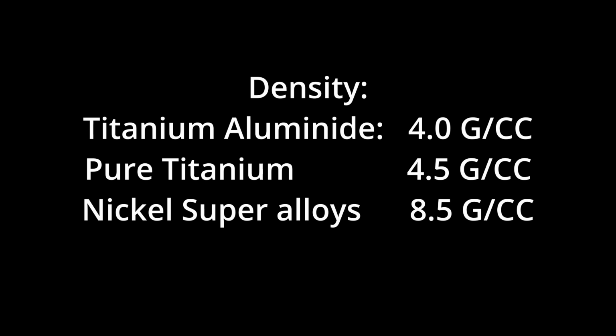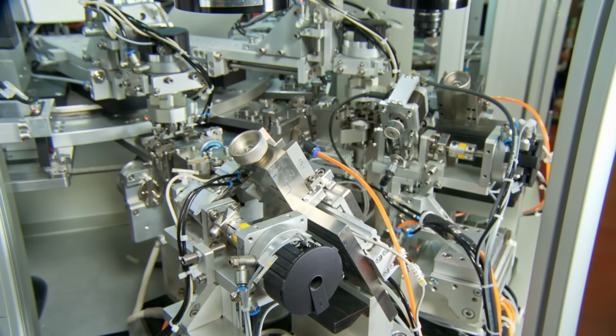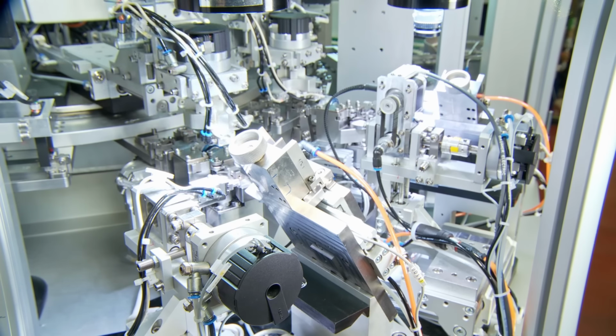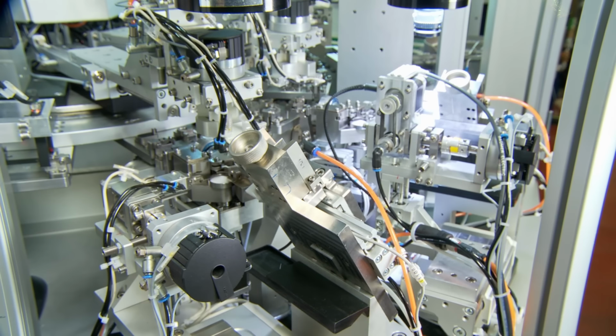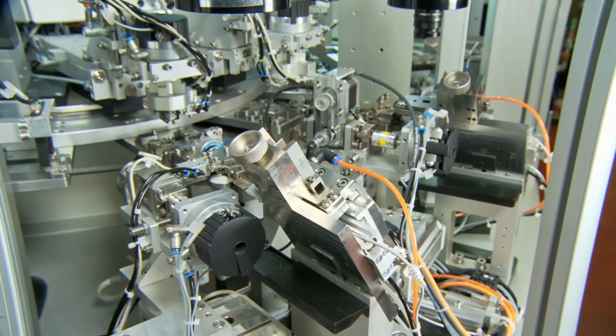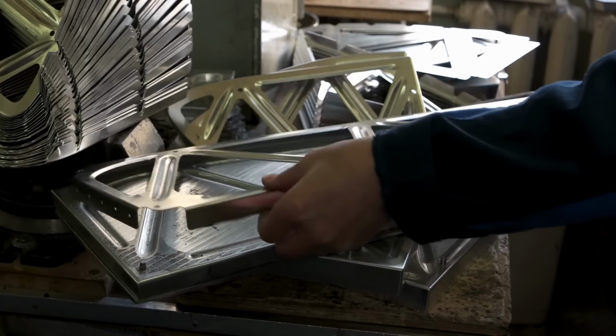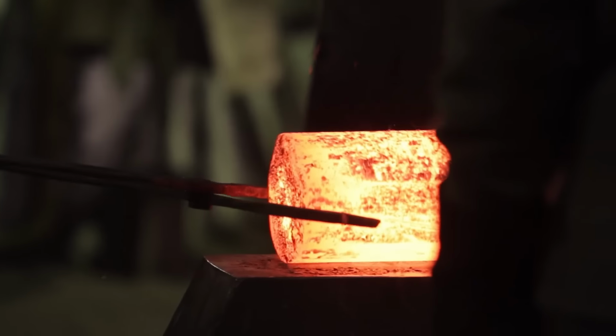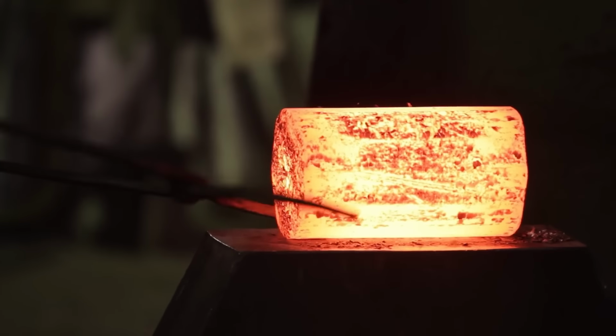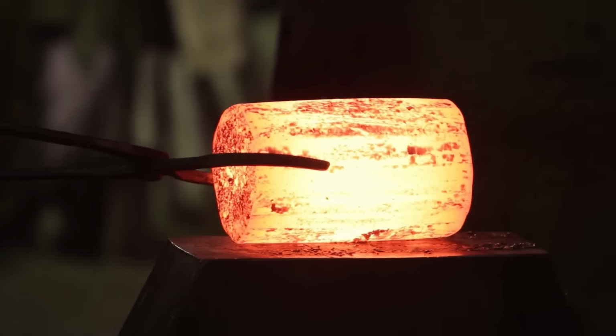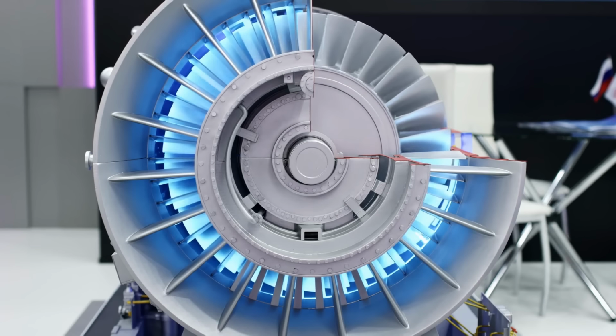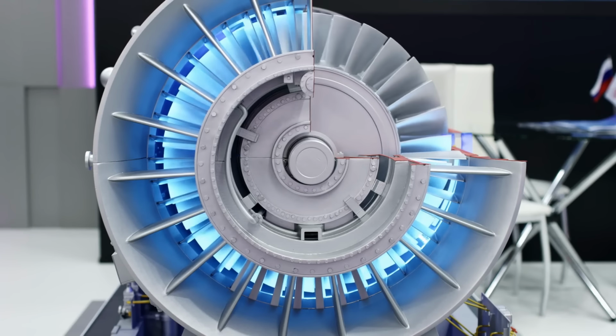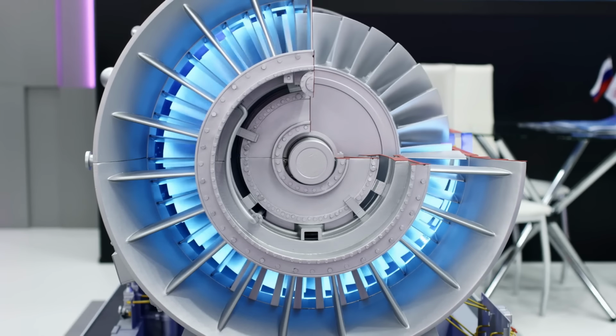Titanium aluminide also remains strong at temperatures of 600 to 800 plus degrees Celsius, and has good oxidation and creep resistance at those temperatures. This makes it a candidate to replace much heavier nickel-based superalloys in some parts of jet engines or gas turbines. Imagine a jet engine's turbine blades, traditionally made of nickel alloy, heavy, but they survive the heat. If you could make them out of titanium aluminide, they'd be half the weight, which could improve the engine's thrust-to-weight ratio and efficiency.